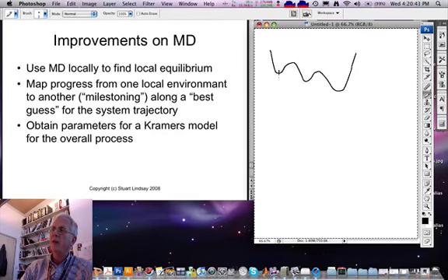can look at this trajectory by breaking it up into small regions like this, running a molecular dynamics simulation within the small region, and asking about the rate at which the particle leaves the region in the forward and reverse direction, and then setting up a set of master equations that couple these motions that were done by sampling a small region of the system and put them together to generate an overall rate of passage for the particle through the system.